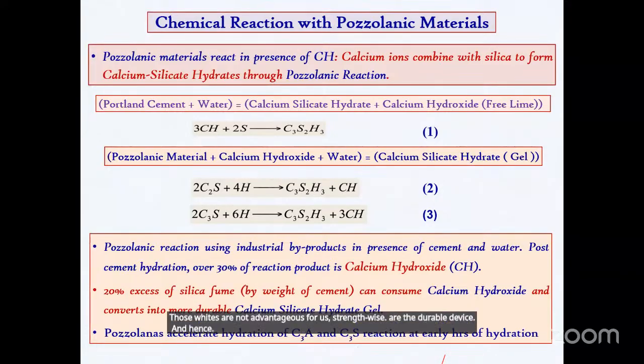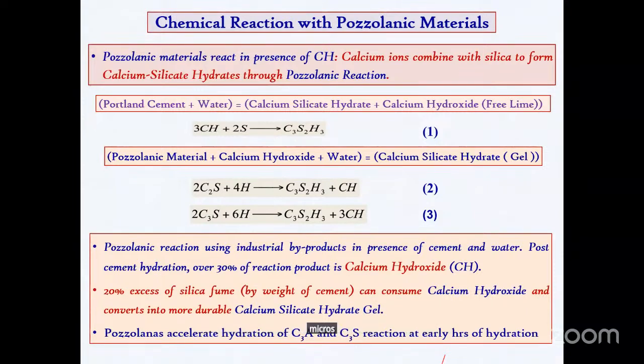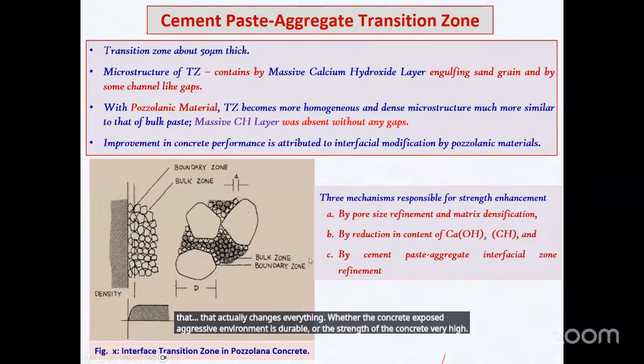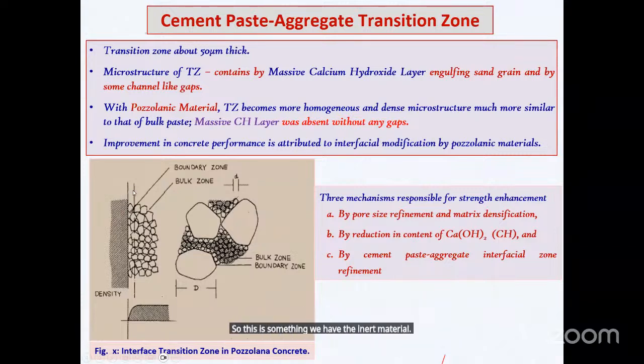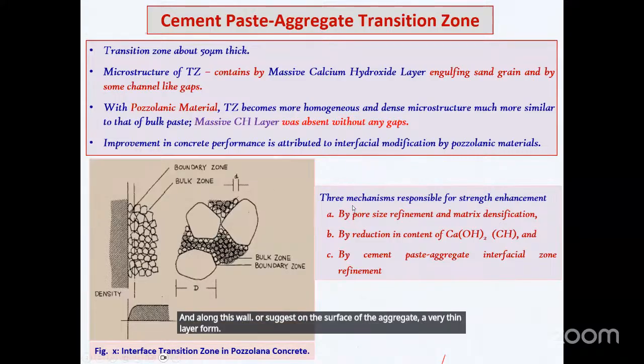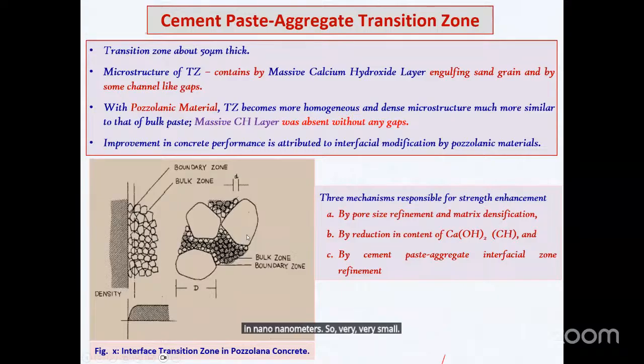And hence, the pore size structure, when you have the byproducts combined with calcium hydroxide, will make the structure microscopically very impervious. So that leads to a small interface, a very impervious interface with very strong characteristics. That changes the whole concept of concrete technology. It changes everything, whether the concrete exposed to an aggressive environment is durable or the strength of the concrete is very high. So we have the inert material, and just on the surface of the aggregate, a very thin layer is formed, in nanometers. So very, very small. That changes the whole idea of the interface.